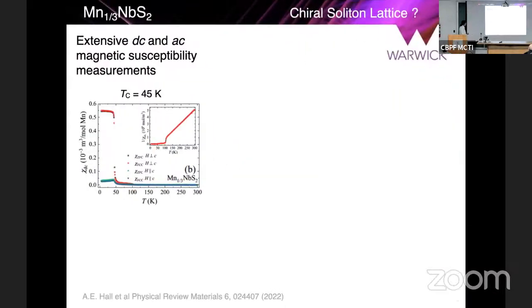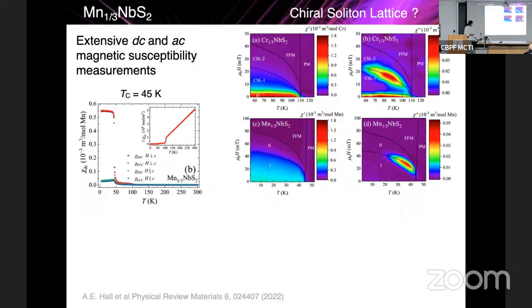So now going to the manganese third niobium sulfide, which I said for all practical purposes is very similar to the chromium third niobium sulfide. So the interest here is in seeing whether this exhibits a chiral soliton lattice, and if not, why not? Okay. So this has a TC of about 45 Kelvin.